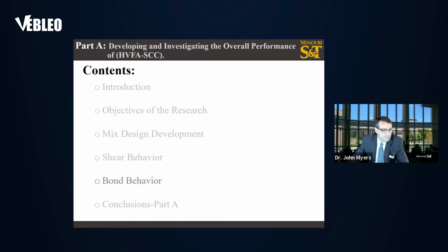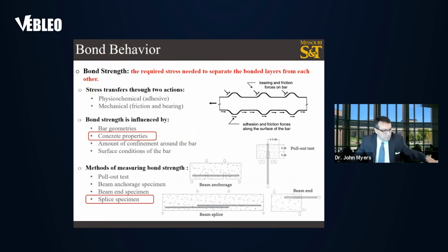Now on to bond behavior. Due to the poor tensile strength of the concrete, steel reinforcement needs to be used to obtain a complete composite behavior. So the tensile strength will be fully transferred to the steel from the concrete. And as you can see, there are two different ways that steel reinforcement and concrete transfer loads. It's by mechanical end bearing of the lugs on the bar as well as friction. And there are 4 different types of tests that can be used to assess the efficiency and how well the bond of steel is to concrete.